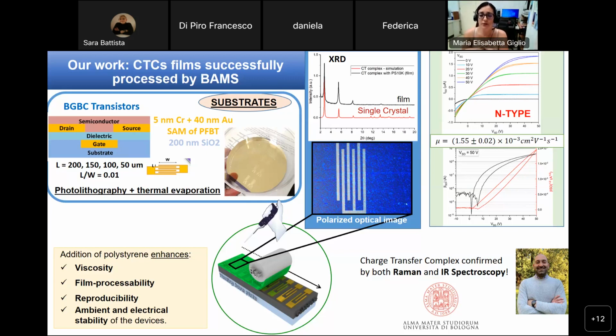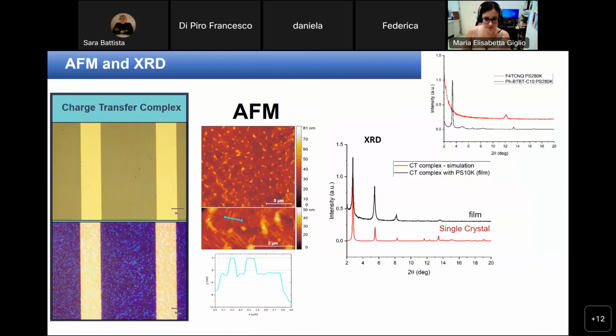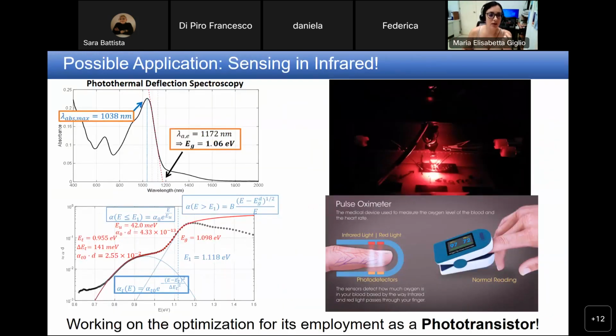And then in the end, by performing the electrical characterization, we could see that we got basically N-type transistors. So in the end, we have an N-type that actually is not very stable, and also the mobility is not really high, because it's of the order of 10 to the minus 3. But the interesting thing here is that by performing photothermal deflection spectroscopy, which is a very highly sensitive technique, we can see a very nice peak in the absorbance in the infrared region.